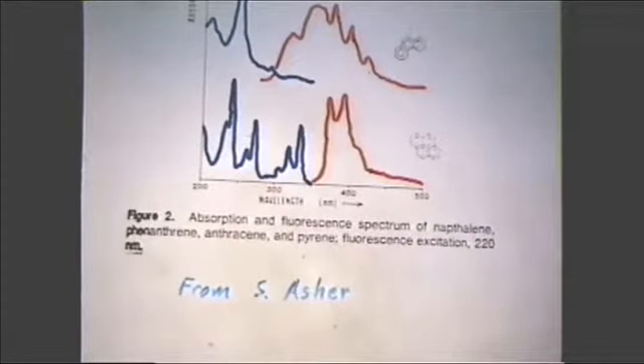So 10 years ago, he did the experiment using a pulsed laser system to generate the UV, and he made a measurement on a coal liquid. He had to look at the liquid in a jet because the pulsed laser beats the daylights out of the sample, because of the very high powers in each of the laser pulses hitting the sample.